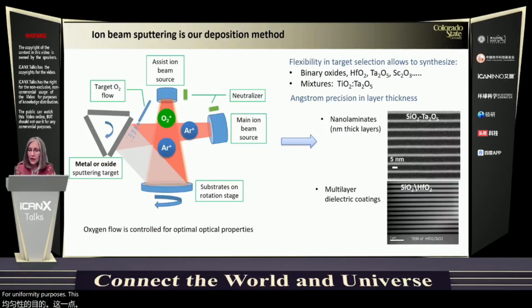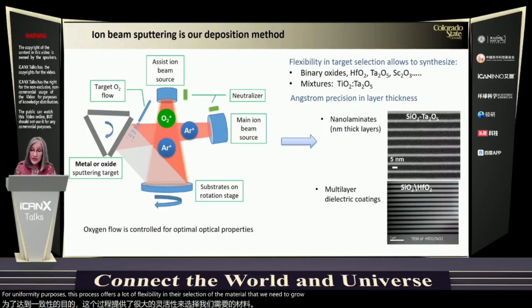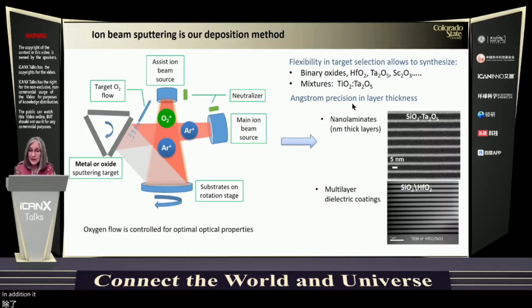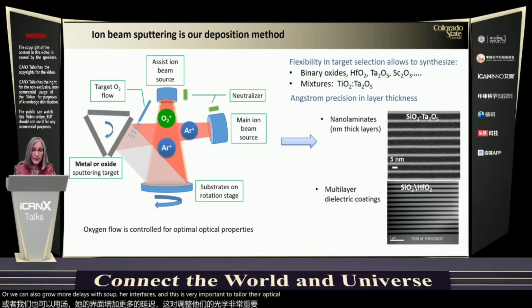This process offers a lot of flexibility in the selection of the material that we need to grow because it depends only on selecting the target. And we can make binary oxides, we can also make mixtures. In addition, it offers angstrom precision in layer thickness. And so we can grow nanolaminates in which each of these layers is a few nanometers thick. This is the case of tantala, or tantalum pentoxide, and silica. Or we can also grow multi-layers with superb interfaces. And this is very important to tailor their optical response.